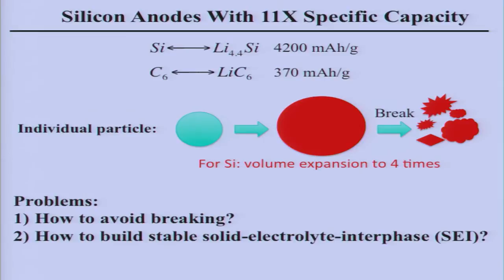So there are 2 major challenges we try to solve. How do we avoid breaking? How do we build a stable solid electrolyte interphase? Remember, each of the silicon particles is going to react with the organic electrolyte. Their surface is so reactive. If they are not stable, they keep expanding and contracting. It won't be stable enough to build up stable batteries. This is the challenge we need to face: solve these 2 problems.